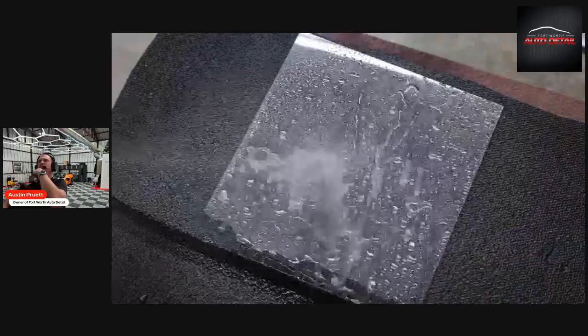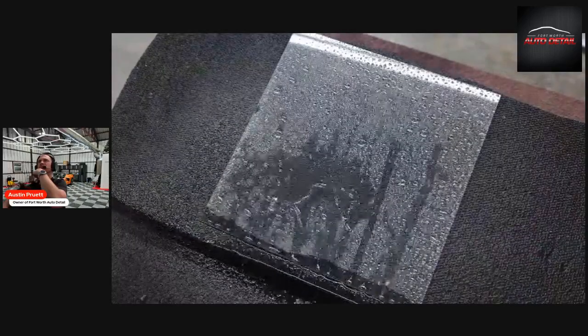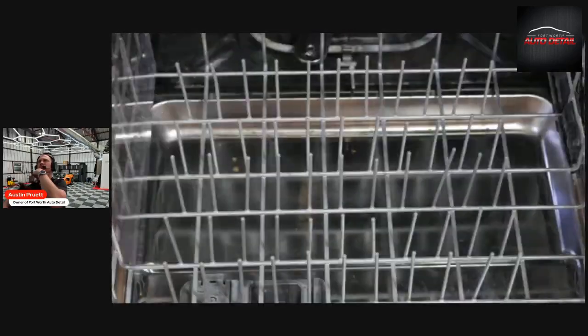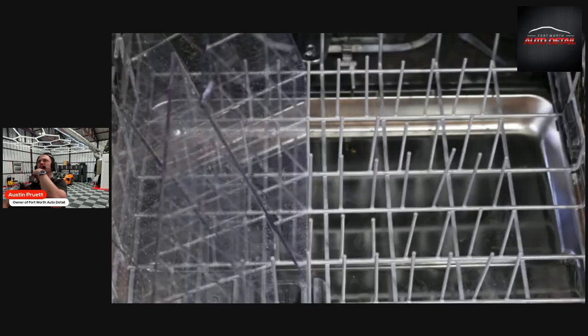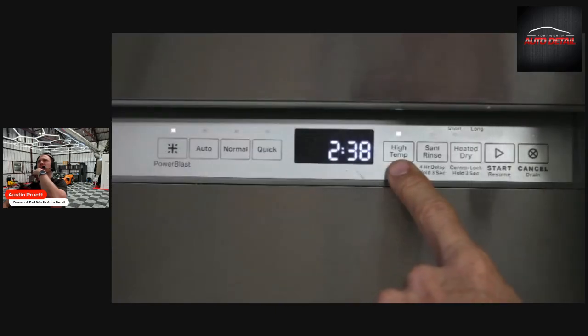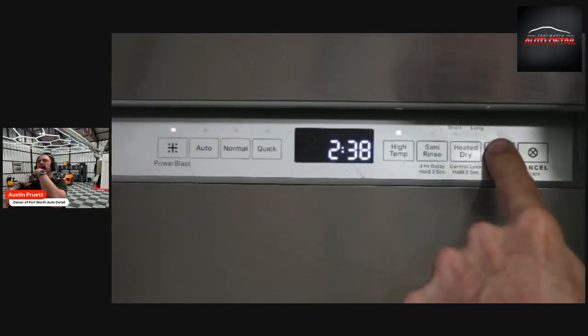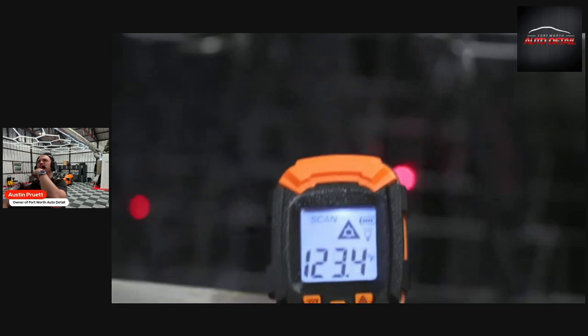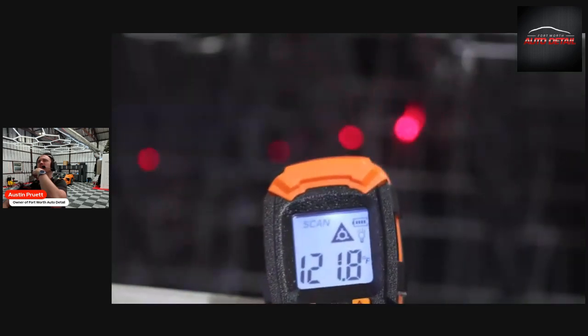Let's go ahead and check in on the polycarbonate test pieces. After 2 hours of warm water spray, all the coatings are still holding up just fine. Direct sunlight exposure creates a lot of heat, so let's simulate those conditions by running 2.5 hours using hot water spray. After just a few minutes, the water temperature is around 120 degrees inside the dishwasher.